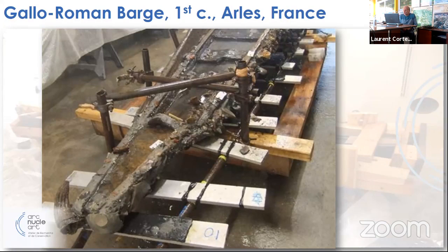These iron plates are a problem for conservation, as we know that conventional PEG treatment will lead to corrosion and acidification of the wood in the presence of metal, due to some salt of metal and sulfur of metal. It will give sulfuric acid. That's why it was decided to treat this section by the so-called combined nuclear treatment, while the whole other section was decided to be treated only by conventional PEG treatment.